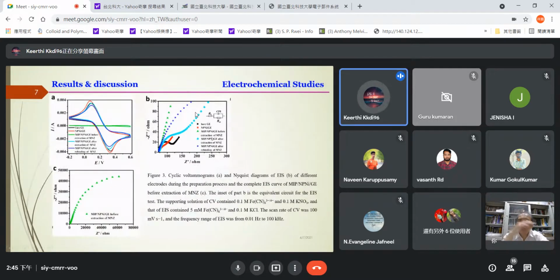Electrochemical studies. The electrochemical behavior of the fabricated electrode was examined using the cyclic voltammetry technique in the probe solution. Figure 3a shows each color's electrochemical response for each modification. The red curve shows the response of the nanoporous nickel GC, which shows a high peak current response, indicating the nanoporous nickel plays an important role in the sensor signal. But when the nanoporous nickel GC was covered with the polyaminophenol film containing the metronidazole, the current response was significantly reduced.